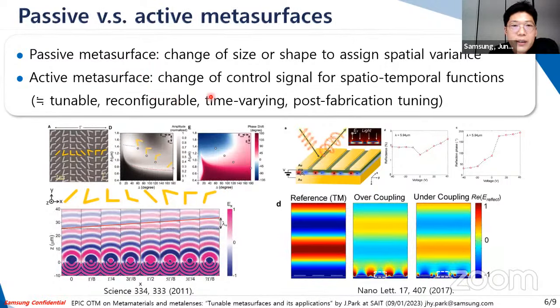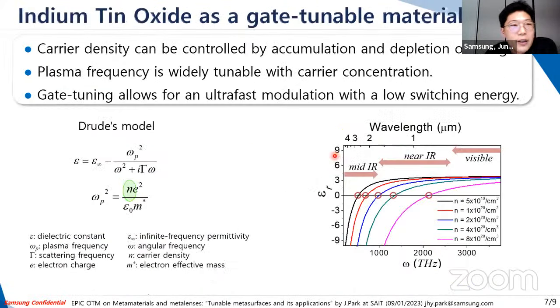In an active metasurface, we change the signal, not just the shape or orientation, and the optical response of the metasurface depends on the applied signal. So we can tune the amplitude, phase, or polarization, both or either. Here we chose indium tin oxide as the material platform to achieve the active, post-fabrication property. The nice thing about using indium tin oxide is that by changing the carrier concentration, we can tune the plasma frequency a lot. This shows the dielectric function as a function of the working frequency.